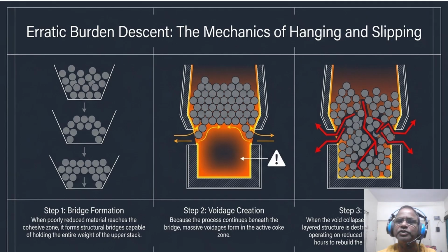Follow the white arrow to step 2. Now void creation. The process continues underneath the bridge, creating a massive empty space in the active coke zone. And finally look at step 3, the slip. When that bridge inevitably collapses, the highly engineered layered structure of your furnace is destroyed.